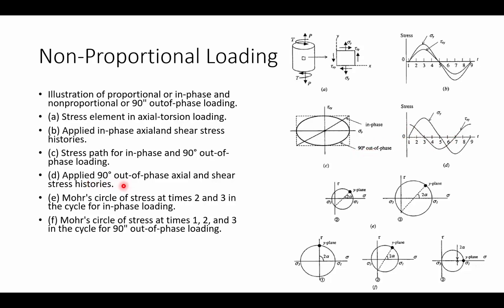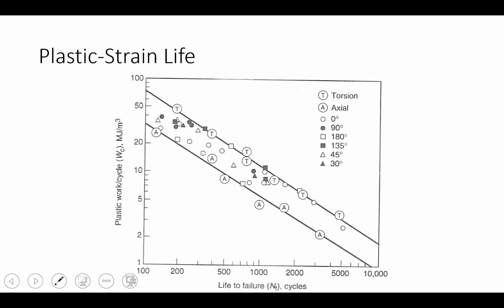When we apply the 90-degree out-of-phase axial and shear stress histories, we see more circle-type plots in the normal stress versus shear stress space. From this non-proportional loading, we're going to produce a different rate of cycles to failure. Conducting many experiments at different degrees of out-of-phase, we can see that depending on the amount of out-of-phase, we exist in between the pure axial case and the pure torsion case — a mixed cycles-to-failure that sits between those two extremes.